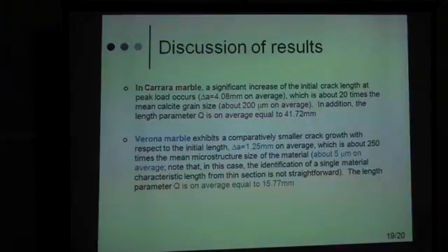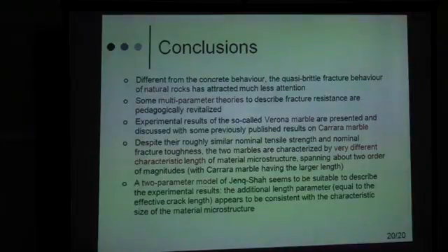In the other marble instead we have a smaller increment of crack, which is much higher than the mean microstructural size, but as I said before, in this case there is no such a regular microstructure of the material, and the Q parameter is on average about 15 millimeters. So what at least we can say from the results is that there is a trend between the delta A, the increment of crack length, versus the material microstructure.